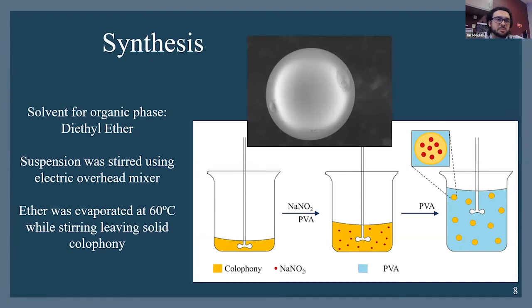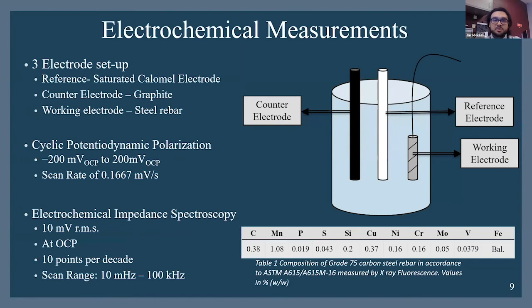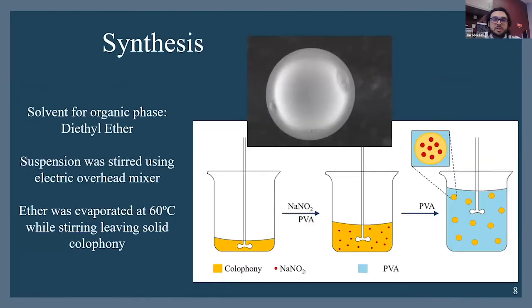So to begin, the synthesis of the microcapsules was done using the solvent evaporation technique, as it is very cost effective, easily scalable, and rather simple. By dissolving our colophony in an organic solvent of ether, followed by stirring with the addition of our corrosion inhibitor aqueous mixture, and then finalizing with this double emulsion by adding an additional aqueous solution, we form these shells with smaller vehicles of the inhibitors encapsulated, as shown in the diagram. And here we see an SEM image of a single microcapsule formed by this method. And then in the end, the solvent was evaporated to form just the solid microcapsule shell.